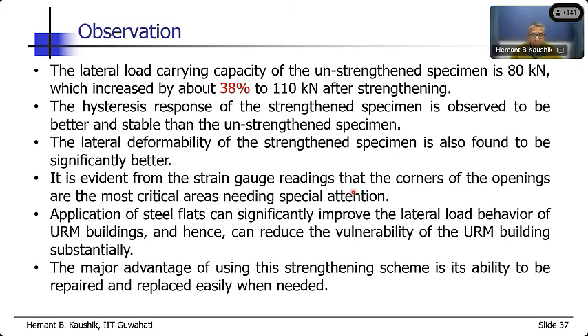And from the strain gauge readings, we found that the corners of the openings are the most critical areas needing special attention because there was more strain at that location. We can significantly improve the lateral load behavior with the help of these steel flats, and we can reduce the vulnerability.